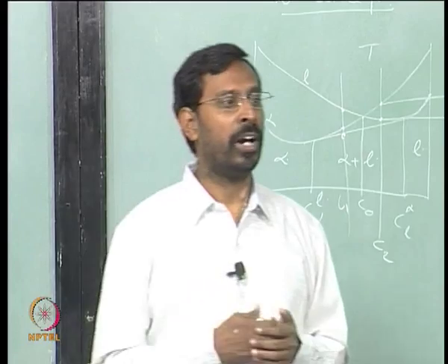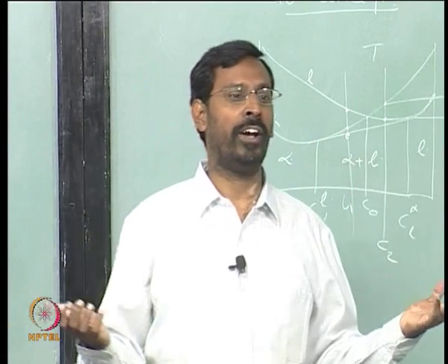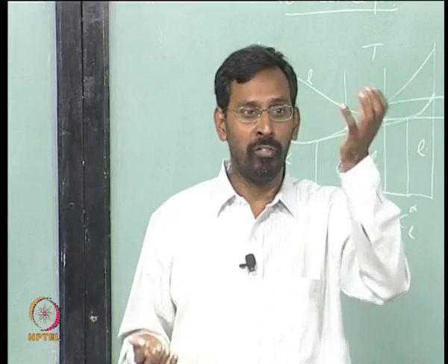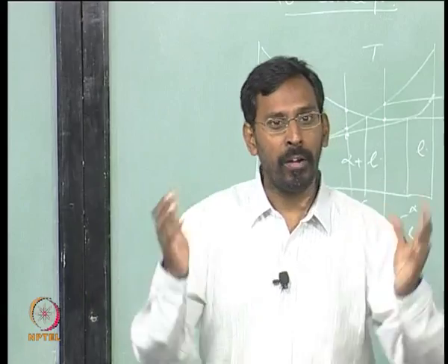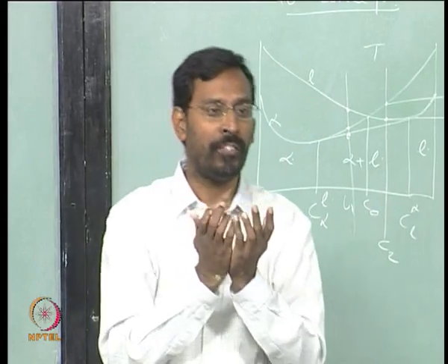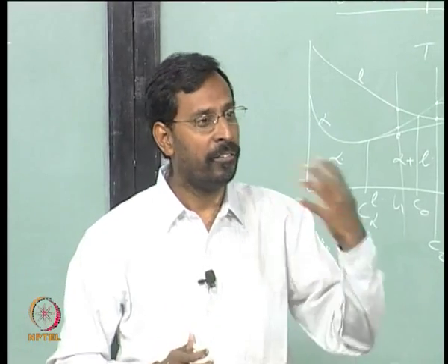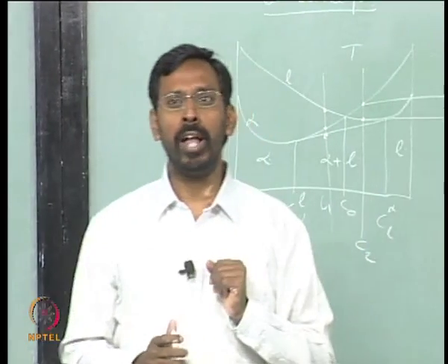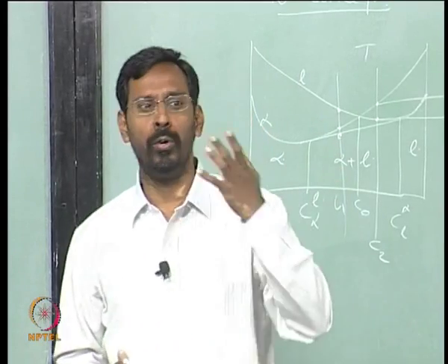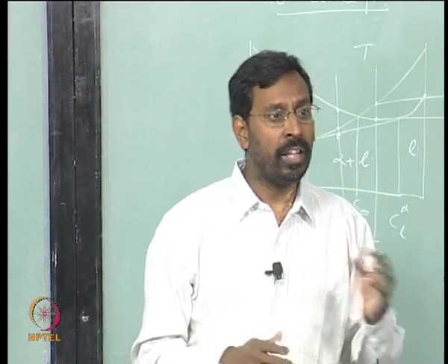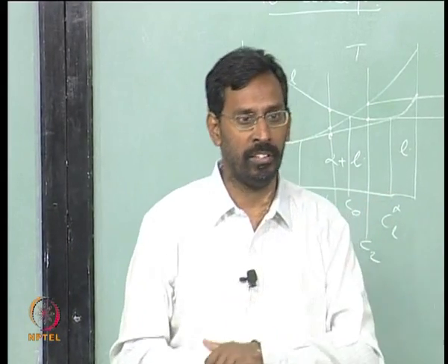So, how to do containerless solidification? Levitate a liquid droplet and allow it to solidify, so that it floats in the air and then solidifies, so that possibly there is no mold effect. So, solidification has to start maybe at the surface of the liquid or within the liquid. What Turnbull thought is that most of the time liquids always have some inclusions inside them, and these inclusions can act as nucleating sites. These are what we call foreign bodies and things like that.